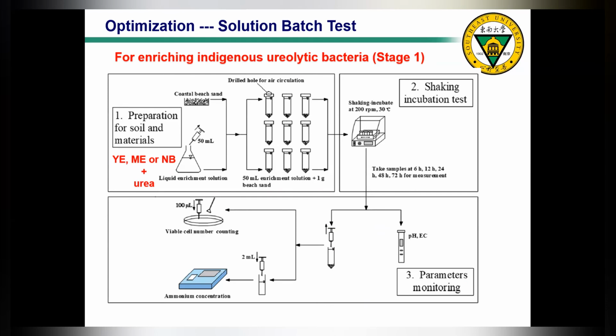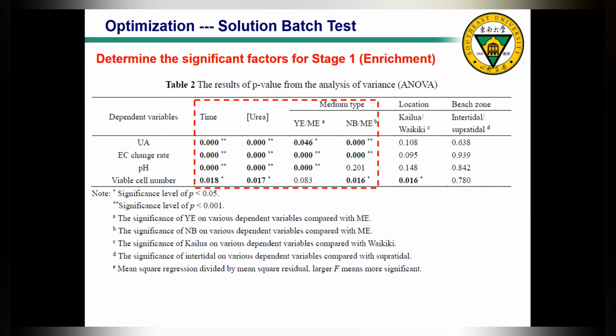Through this test, we performed the analysis of variance to get the p-values. A very small p-value means that a certain variable is very significant. So from this analysis, we can clearly see that the incubation time, or the stimulation or enrichment time, the concentration of urea in the enrichment solution, as well as the medium type, are the most significant factors that may affect the enrichment stage.